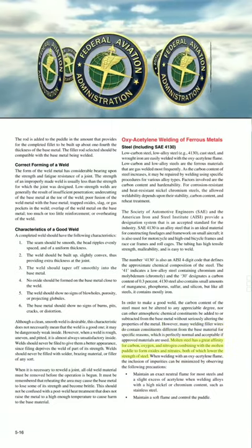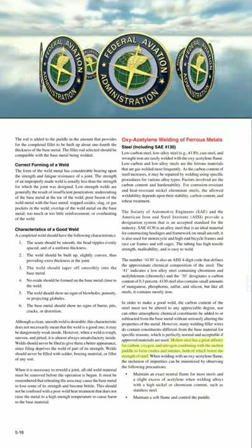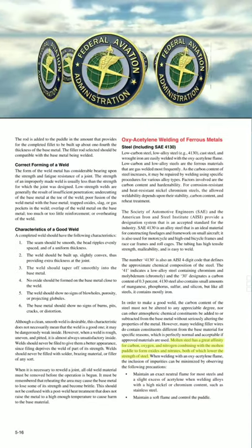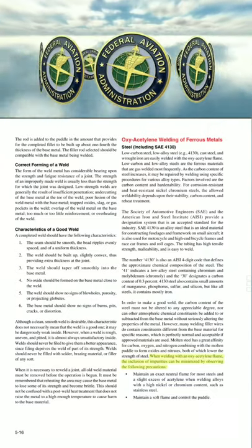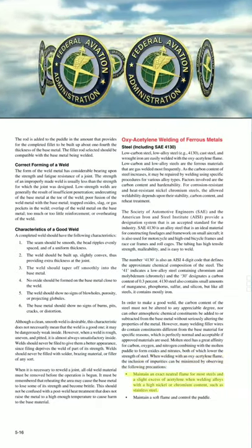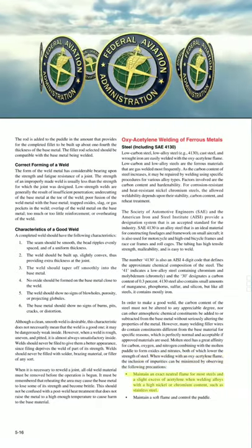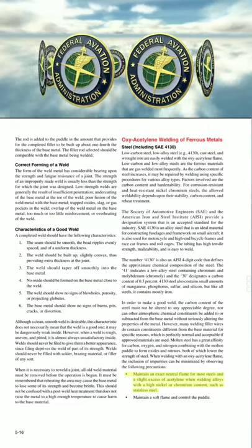Molten steel has a great affinity for carbon, oxygen, and nitrogen, combining with the molten puddle to form oxides and nitrides, both of which lower the strength of steel. When welding with an oxyacetylene flame, the inclusion of impurities can be minimized by observing the following precautions. Maintain an exact neutral flame for most steels, and a slight excess of acetylene when welding alloys with a high nickel or chromium content, such as stainless steel.